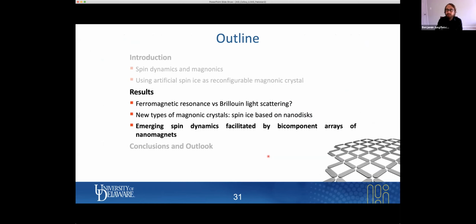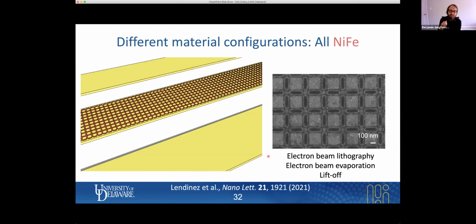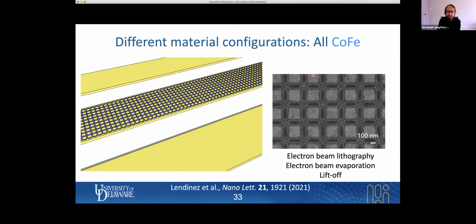All right, so in the remaining time of my presentation, I want to introduce a new type of artificial spin ice. So this is a bicomponent array of nanomagnets, and we got really excited about these results. So first we did 2 control measurements. We fabricate as before using electron beam lithography, e-beam evaporation, and lift off our lattices. So first we have here control measurements, just only nickel iron, so permalloy. And I show this here in red color superimposed to the SEM image. And then we do a lattice with only cobalt iron, and I'm showing this here in blue color.